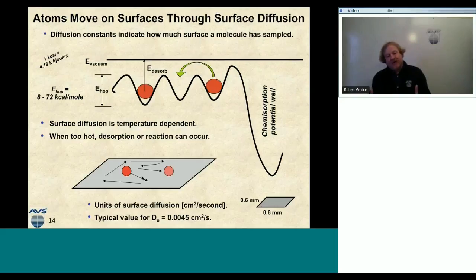And so just to calibrate you, what that means is that with that surface diffusion constant, I sample a surface that's about 0.6 of a millimeter by 0.6 of a millimeter. So with that surface diffusion constant, a molecule that lands on that surface is just going to go around and sample all that very small surface area of 0.6 millimeters by 0.6 millimeters. And so I leave that to you as an exercise to determine how many surface sites are in this 0.6 millimeter by 0.6 millimeter square, and then you have an idea when a molecule comes onto a surface and diffuses with a certain diffusion constant, how many surface sites this molecule is actually sampling at a given temperature. And so if anyone wants to calculate that number, you can send it to us, and we could talk about it back on the webinar.